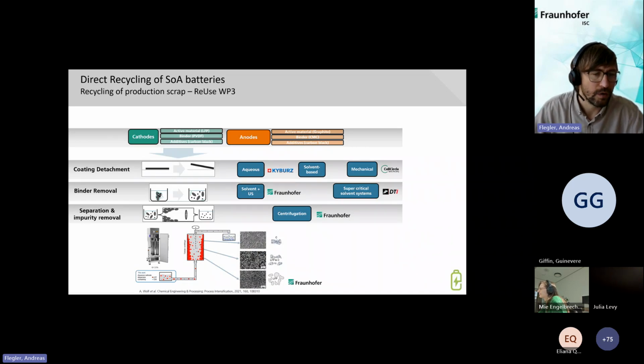Here we are focusing on a centrifuge process. We use a semi-continuous centrifuge. When we have separated the anode and cathode active materials from the carbon black, we pump this dispersion into the centrifuge. Due to a difference in particle size and density, the LFP particles will remain in the centrifuge, and the smaller particles like carbon black will go out in the centrate. So we can concentrate the LFP particles without impurities and go further to the regeneration process.